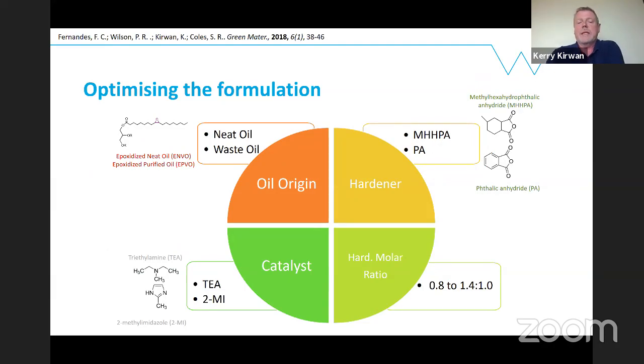So what we then carried on looking at was all the different types of variables that could influence our properties. So again, neat oil and waste oil. We looked at different types of hardeners, the ratio of the hardeners that we used, and different types of catalysts. And what we found with a very long 3-year piece of work was that the molar ratio was the important bit, not the waste or the source of the oil, which is quite nice because it means we can take waste oil, we can treat it, and it doesn't have a huge influence upon the final properties of the composite that comes out. It's the hardener choice and molar ratio that does.